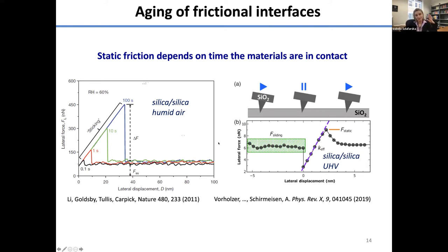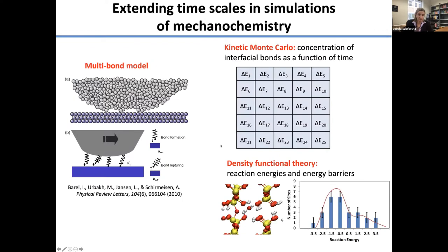So how do we study chemistry and coupling to stresses over long time scales and over large length scales? These are the multiscale models. Let's start with time scales. There are different models developed in the literature. I'm going to totally focus on the one we developed, which is based on the so-called kinetic Monte Carlo technique. And in principle, it's fairly simple. We represent the surface as a number of different bonding sites. So we have to understand the chemistry of the surfaces.